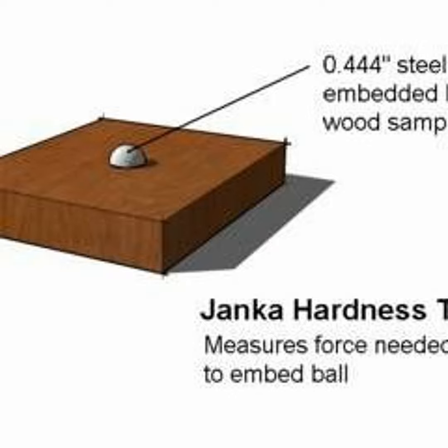Now, I talked about porosity, so let's move on to that. Hardwoods have pores. They really can either be ring porous, diffuse porous, or semi-ring porous. Perfect example of a ring porous wood is red oak. It's got really large pores, and they are all clumped together in very specific rings. The early growth wood of red oak, early in the spring, grows very, very fast, and it's got very wide open pores, and all those pores are grouped together in that ring. In between those groups of pores is the late wood, and it is quite dense. The hardness of red oak is about 1290 something pounds per square inch.